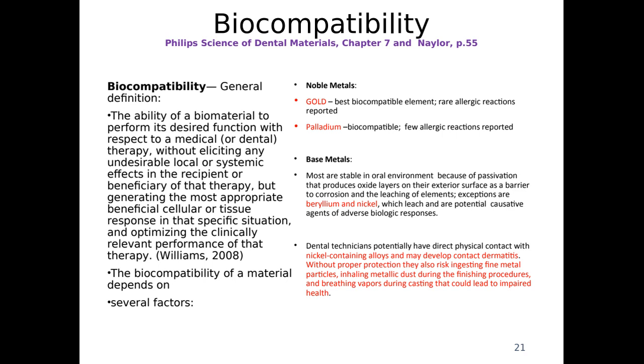Noble metals, gold, it's the best biocompatible element. There are very, very rare allergic reactions reported. Palladium, it's a very compatible material. Base metal, those are the most stable in oral environment because of passivation that produces an oxide layer on the exterior surface as a barrier to corrosion and the leaching of the element. Exceptions are beryllium and nickel, which leach and are potential causative agents of adverse reactions in patients. Dental technicians potentially have direct physical contact with nickel-containing alloy and might develop contact dermatitis. Without proper protection, they also risk ingesting fine metal particles, inhaling metallic dust during the finishing procedures, and breathing vapors during casting that could lead to impaired health.